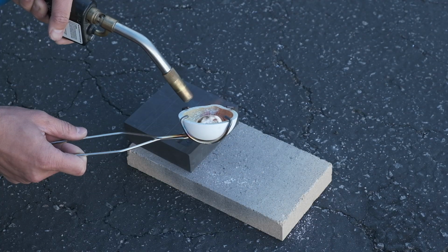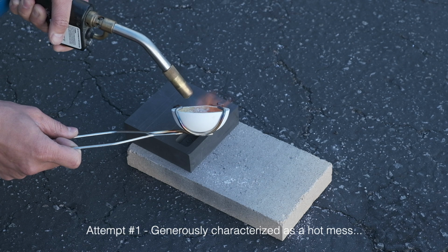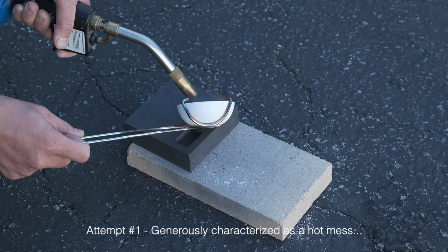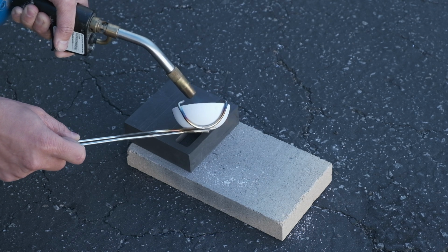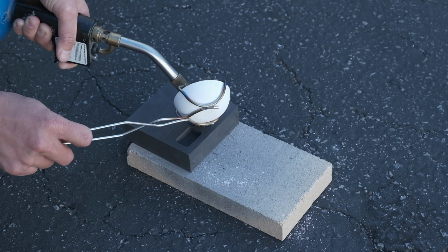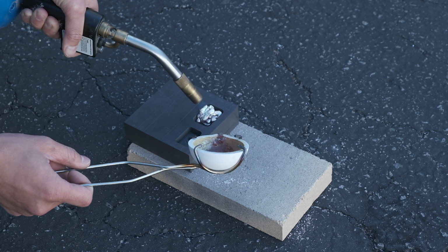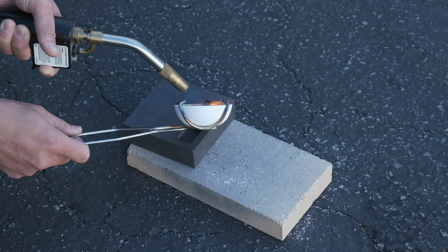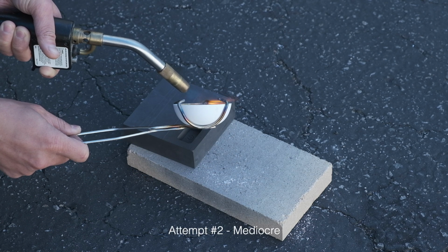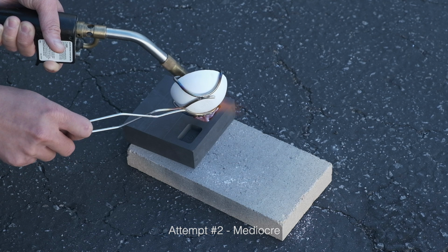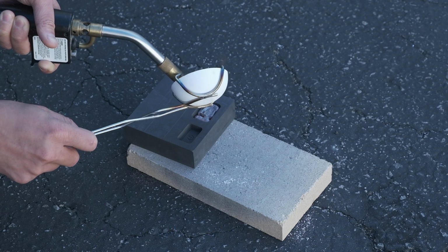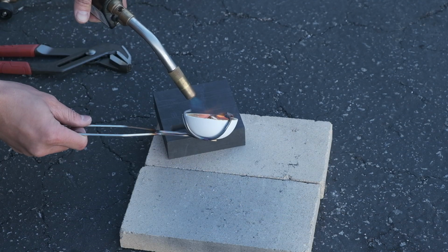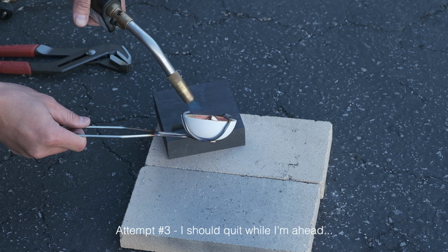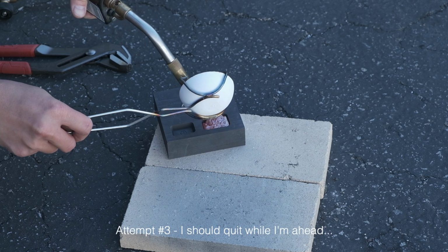In a toaster oven, I was preheating my graphite mold to try and reduce any thermal shock, but to really achieve any practical improvements in the surface finish of your casting, you really need to bring up that temperature with a torch. I had some issues getting my silver to flow into all the tiny little features, and that's entirely on me for not knowing when, where, and how much heat I should be applying to both the melting dish and the mold. Over time, graphite will start to develop pitting and small pieces might flake off. This mold will not last forever, and that's okay.